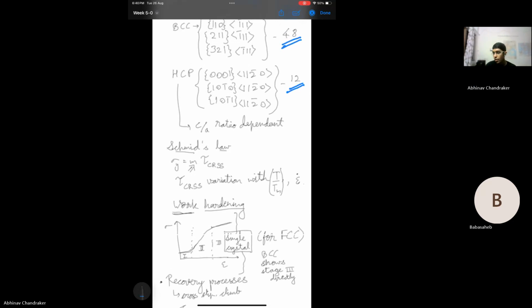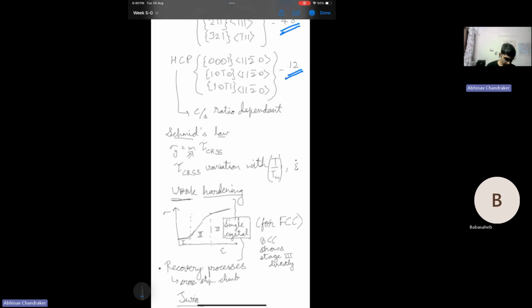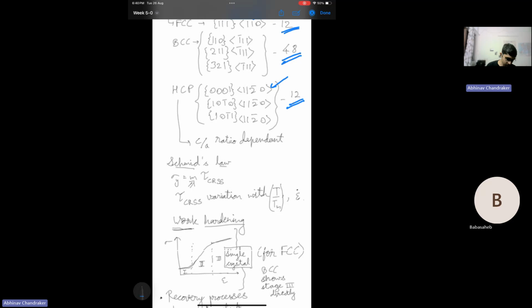HCP crystals will have different Peierls stresses or CRSS based on the c by a ratio. In some cases, we will see maybe later, basal slip might be more favorable. This is basal slip, this is the basal plane. Basal slip tends to be favorable for those which have higher c by a ratio, that is more widely spaced basal plane. In some cases, the prism or the prismatic face is more favorable as a slip plane. That happens for lower c by a ratio. So usually for metals like magnesium, basal is more favorable, while for those like zirconium or titanium, prismatic is more common.